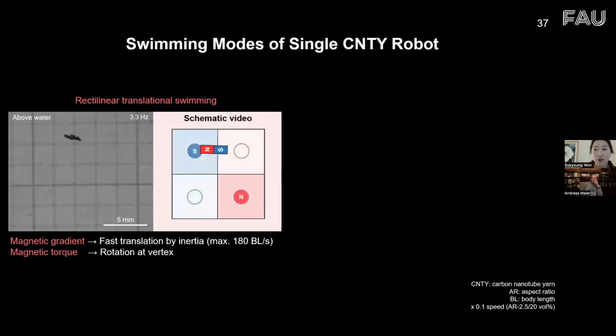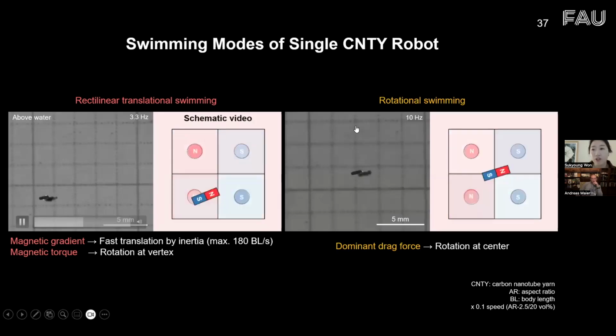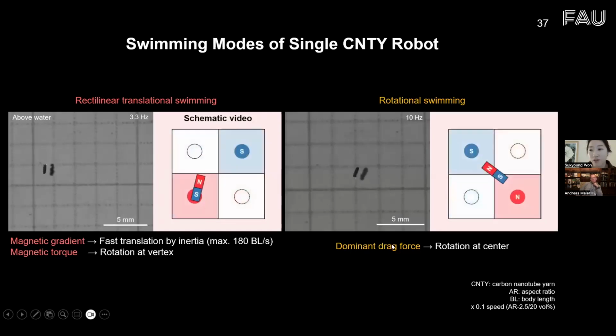And these microrobots were actuated by the pulsed electromagnetic field. This basically makes a rotating magnetic field, and these robots can show translational swimming motions along the magnetic field gradient, and it shows a really fast swimming behavior, maximum 180 body lengths per second. At increased magnetic frequencies, the robots show rotational swimming at the center because of the increased drag forces relative to the inertia force applied to the swimming robots.